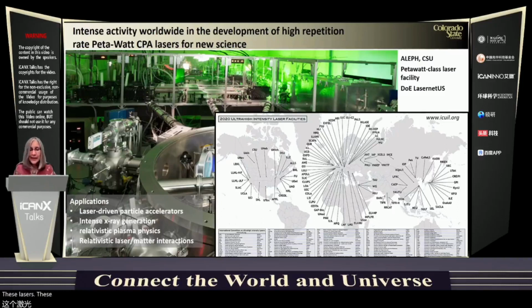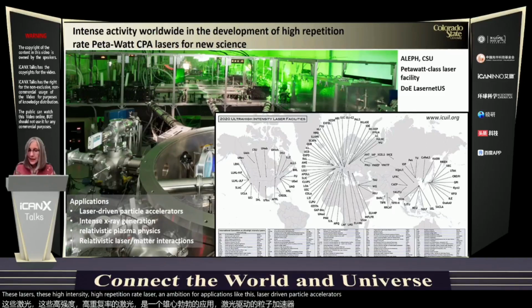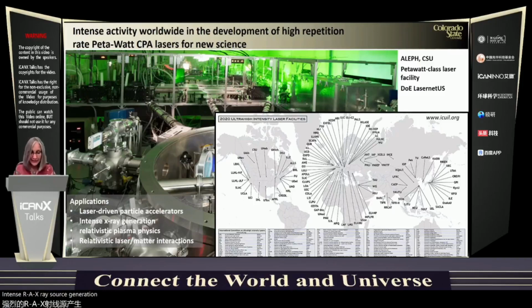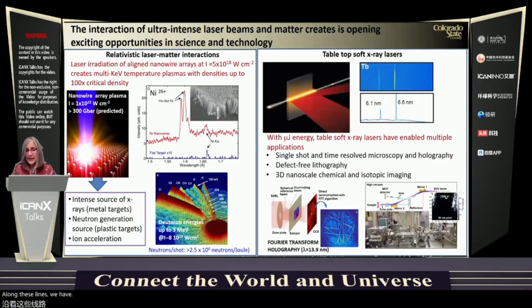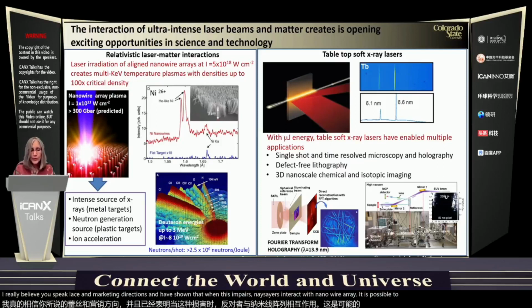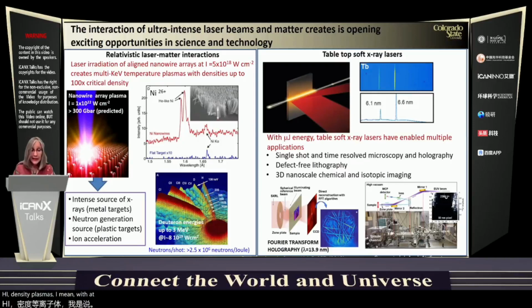These high intensity, high repetition rate lasers are envisioned for applications like laser-driven particle accelerators, intense X-ray source generation, and relativistic laser-matter interactions. Along these lines, we have used these lasers for some applications. Jorge Rocca at Colorado State University has used the lasers to investigate relativistic laser-matter interactions, and has shown that when these intense lasers interact with nanowire arrays, it is possible to produce high-density plasmas, with densities and pressures similar to that of stars. These dense plasmas are intense sources of X-rays if metal nanowires are used, or neutrons if plastic nanowires are used.